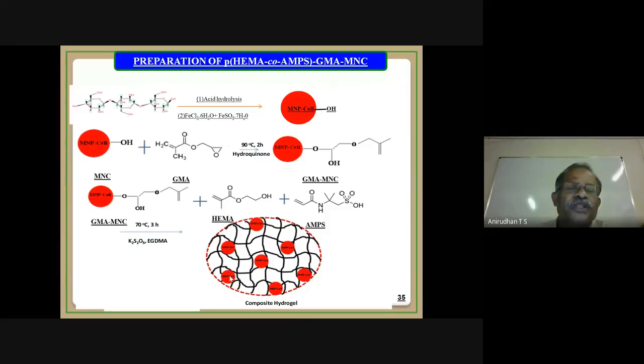So we start with cellulose. Cellulose is treated with acid hydrolysis, followed by incorporation of magnetic particles. We have MNP, meaning magnetic nanoparticle. Cellulose is associated with OH groups, and this is treated with glycidyl methacrylate at a temperature of 90 degrees in the presence of hydroquinone, and we have glycidyl methacrylate grafted magnetic nanocellulose.